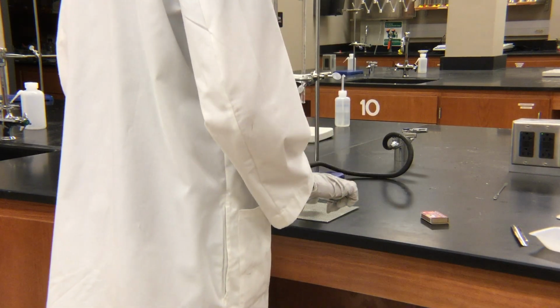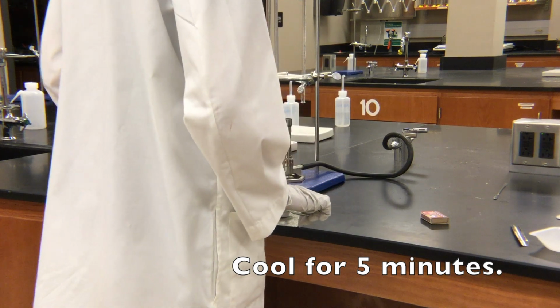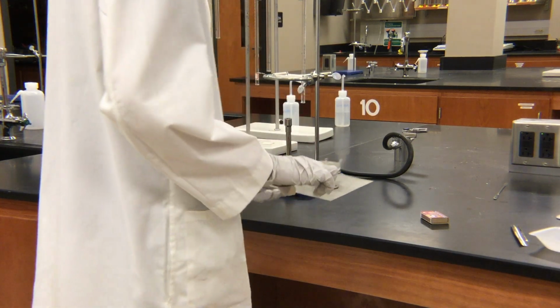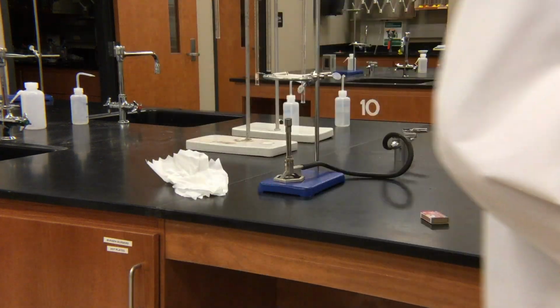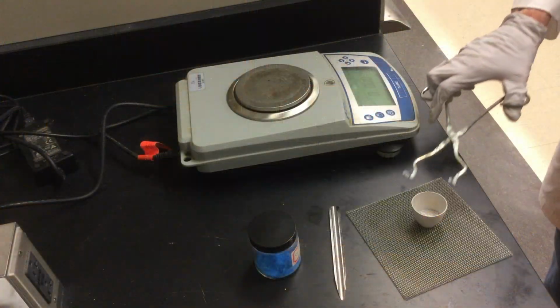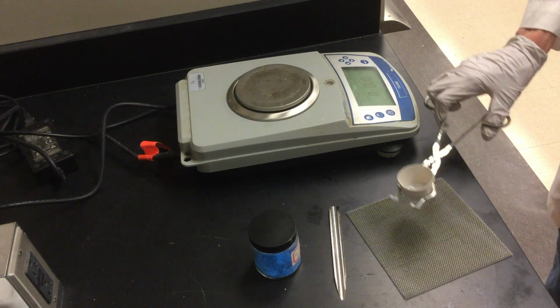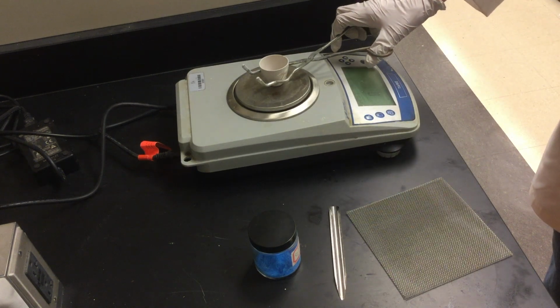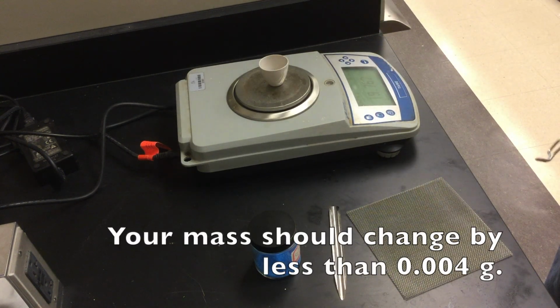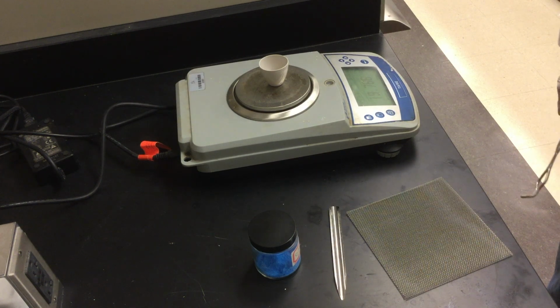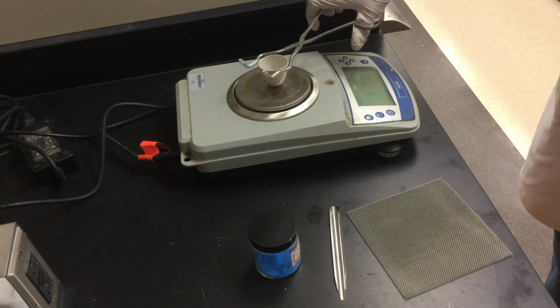Once again, allow the sample to cool for 5 minutes, then transport it to the balance to weigh. After the third heating, the mass should be within 0.004 grams of the second heating. This indicates that all of the water has been driven off.